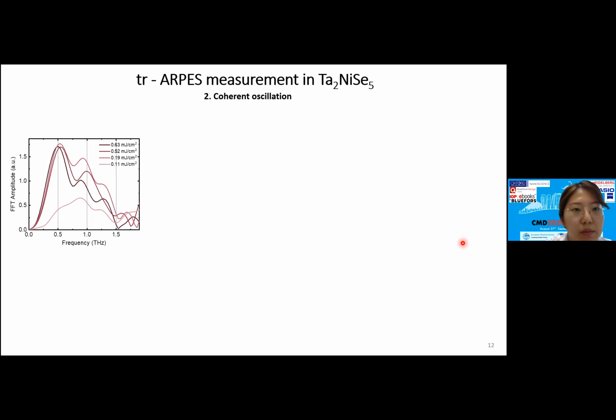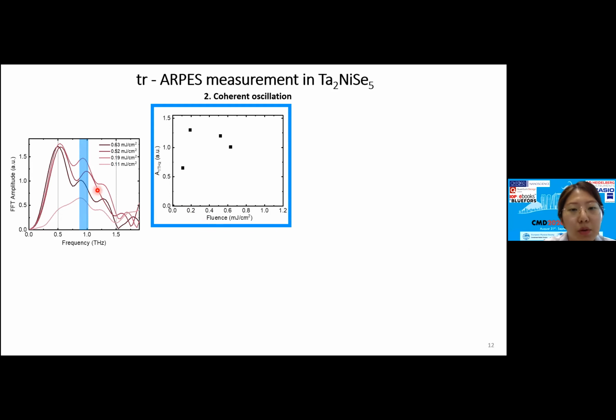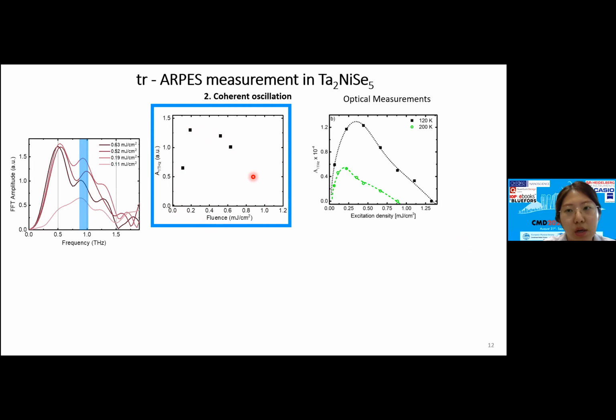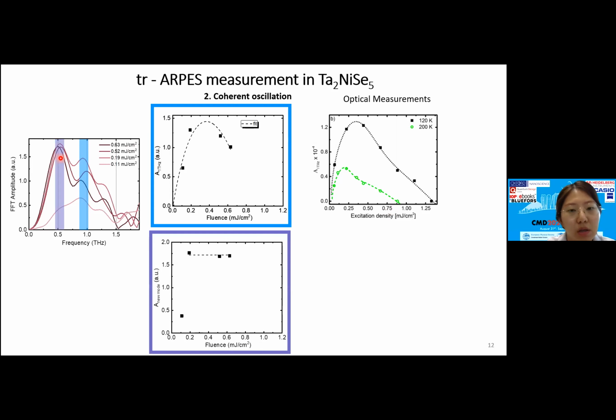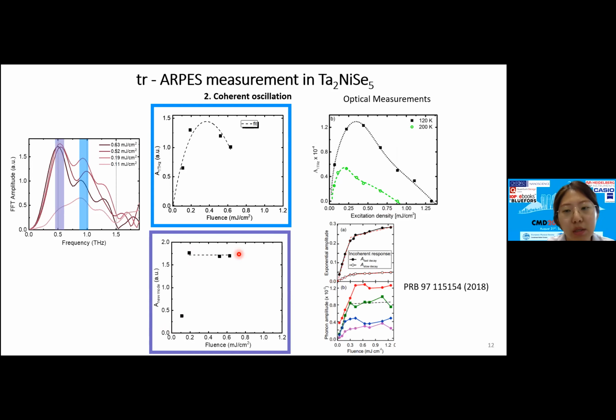The FFT of these oscillations gives mainly two modes. The first mode is at 1 terahertz, which we already saw in the optical pump-probe measurement, and as a function of fluence, it starts increasing but then depletes. That is similar to the optical pump-probe measurement, because this 1 terahertz phonon mode is coupled to the condensation. So this shows similar behavior, but we found another interesting mode which sits at 0.5 terahertz and which increases but saturates. And this we can also see in the coherent phonon dynamics in previous work.